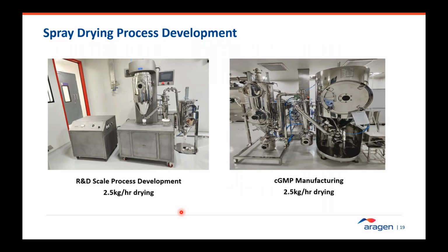So the last piece of the development is process development. Usually spray drying is the go-to process because of minimal compound requirement and ease of process. And in some cases where the solvent solubility is so low for the compound, one may choose a hot melt extrusion as a choice, which requires typically at a clinical phase a lot of material to optimize the temperature, develop the process.